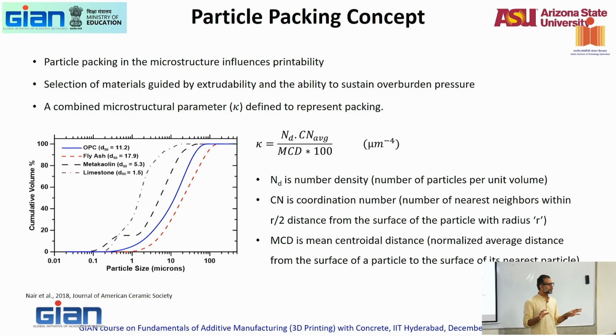0.905 is what you can get by packing all these different size particles. But those are spherical particles. When you pack those particles now, if you have, say, cement, fly ash, silica fume, limestone, different types of particles with different size fractions, then the nearest neighbors are going to be different. Hydration changes when the nearest neighbors are different. So when you have limestone as fine filler, when you have a filler effect that is happening, and when you want these fine fillers to do nucleation, you want them to be distributed as much as possible, closer to cement particles to hydrate and all of that.